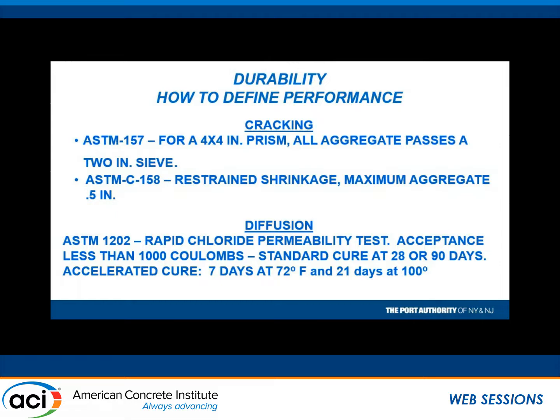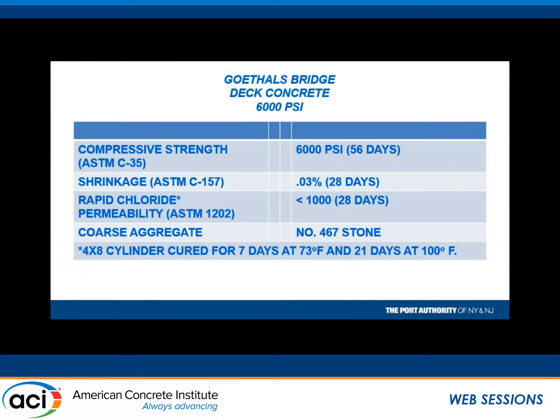7-day curing at room temperature, 21-day curing at 100 degrees, and people say that that should mimic the life of that concrete in 6 months. I don't know if it does or doesn't, but when we've cored concrete in place, even on this Goethals Bridge, 6 months, a year out, for whatever reason we had to take cores, the Coulomb counts on those cores were always less than 500. Okay, so this is not a bad test to give you an idea of how impermeable that concrete is. So Coulomb counts below 500 are pretty damn good in my book.